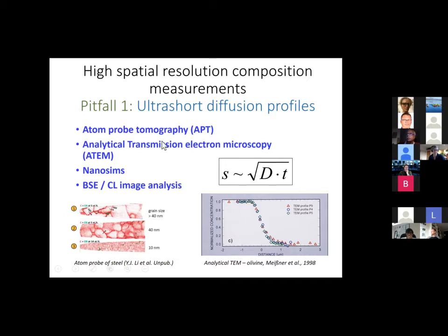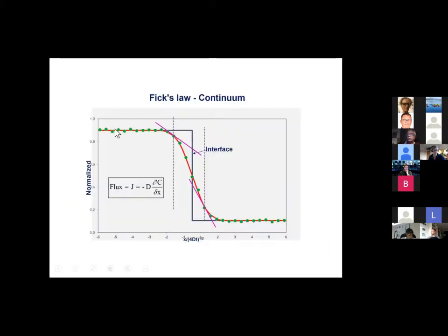Now, people do that. People have been using these to get timescales, to model diffusion, and there is a problem. So let's go back to our Fick's law. Let's go back to what we were doing here. We were looking at this red concentration profile. We're looking at the purple slopes here, and that gives you the flux and the diffusion rate and so forth. Now, what happens at the beginning when you have this steep gradient here? What is your dC/dx at this discontinuity? It's actually not defined.